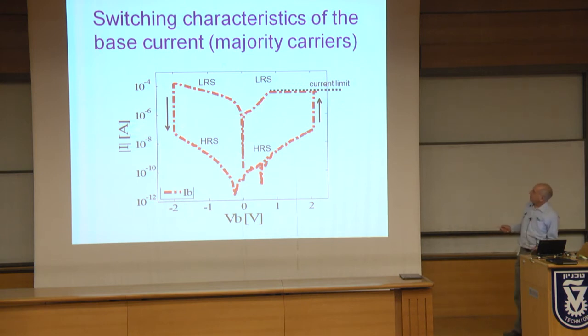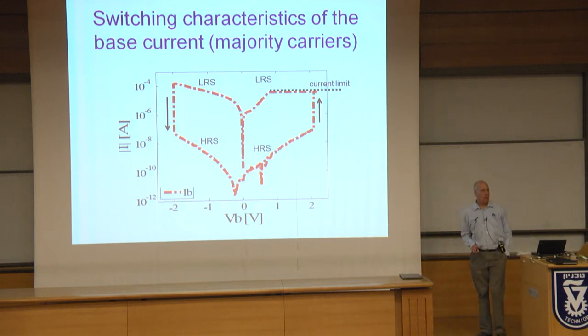This is how switching is looking when we're just looking at the base current, namely the majority carrier current. This is exactly the same as an MIM metal insulator metal structure would behave. This is the set operation. We have to limit the current, otherwise we get a hard breakdown and the device cannot be recovered. And at negative bias, we can get to the high resistance state again. This is nothing new about this. We would get exactly the same characteristics if we would just look at a metal insulator metal two-terminal device.